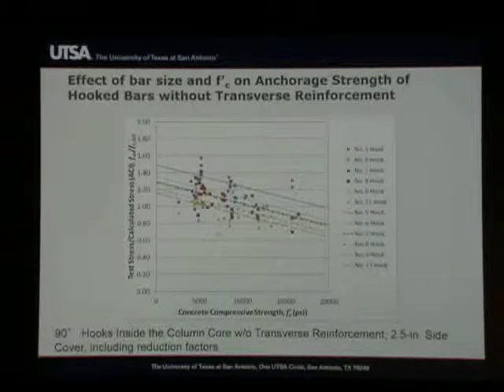This is because in these analyses, and all the analyses that I'm going to show, we used a statistical technique. It's called dummy variables analysis. We assume that the slope of all these populations for different hooks are the same, and we do the regression and we determine the intercept for each one. And so the intent of doing that is to isolate the effect of the different variables, in this case, concrete compressive strength, for subpopulations of hooks. So for example, in this graph, what we're evaluating here is bar size.